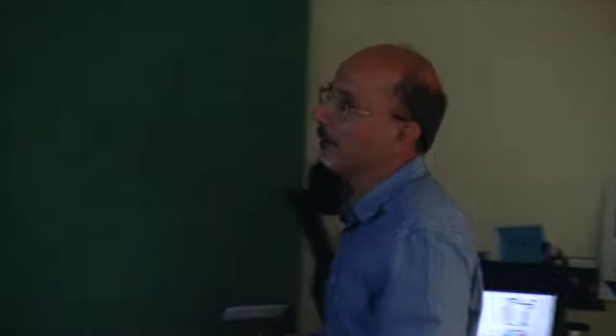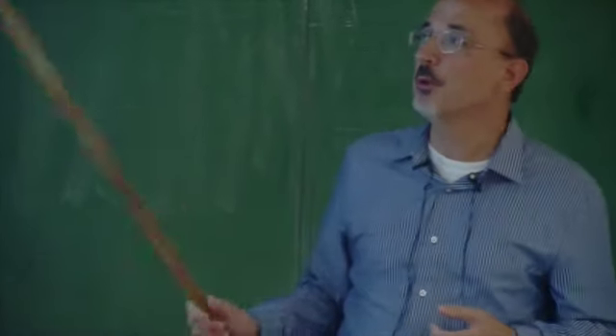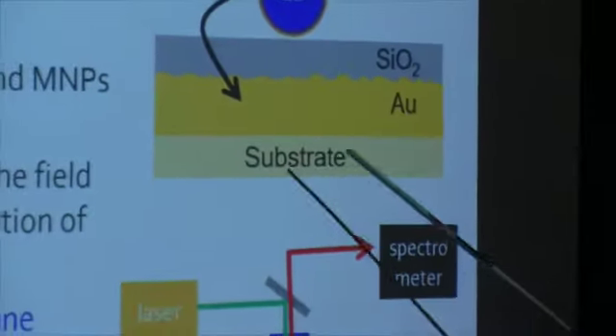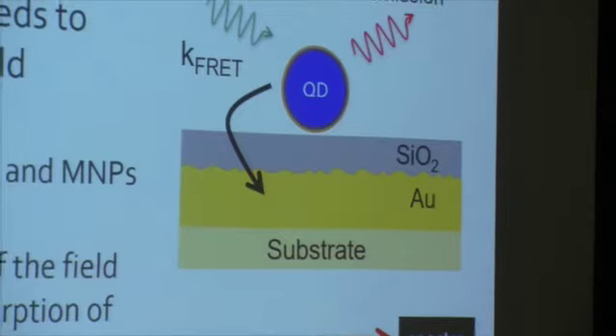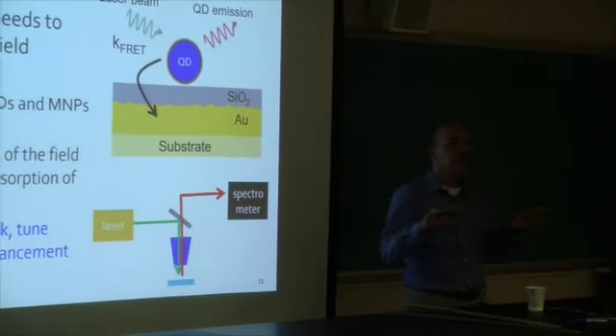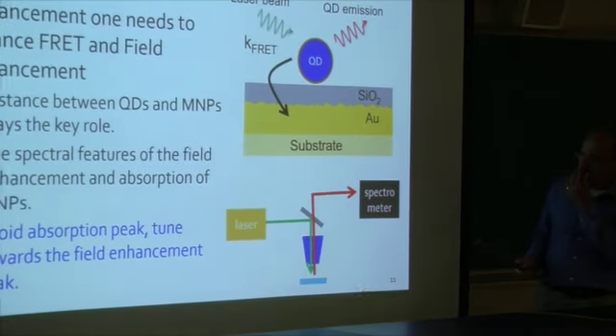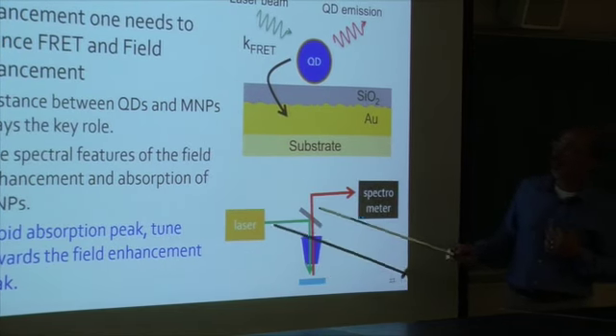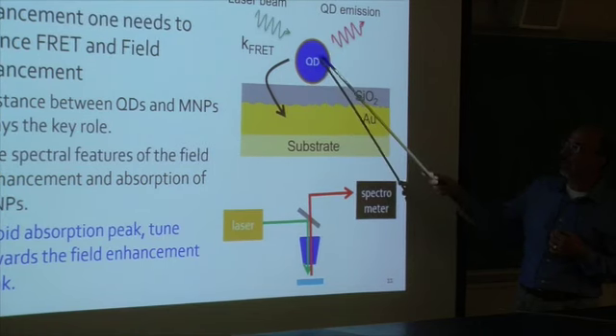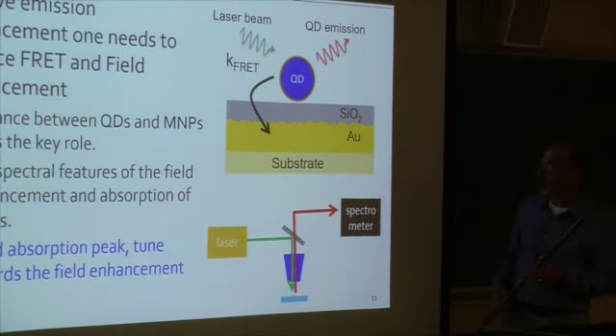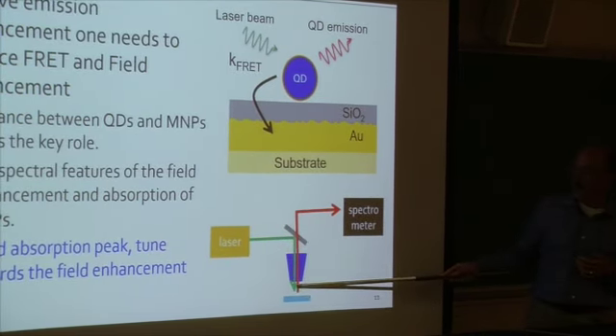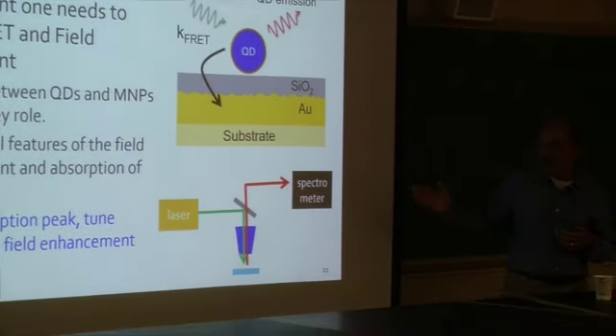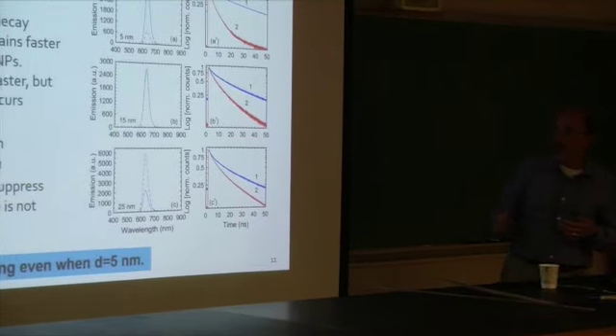The fact is that quantum dots are very good absorbers and give off emission very nicely. I will show you in a slide a couple of slides later how bright they are. So what we do to show this is start from a regular, simple substrate and put gold, but you have to make sure the gold is rough. It shouldn't be smooth. Then you put silica on top and quantum dots on top. We adjust the distance between these two and look at the lifetime of the quantum dot, as simple as that. This is the setup, very simple. A laser comes, hits the quantum dot, and we grab the emission of the quantum dot into the spectrometer or lifetime measurement. And these are the results that we obtain.